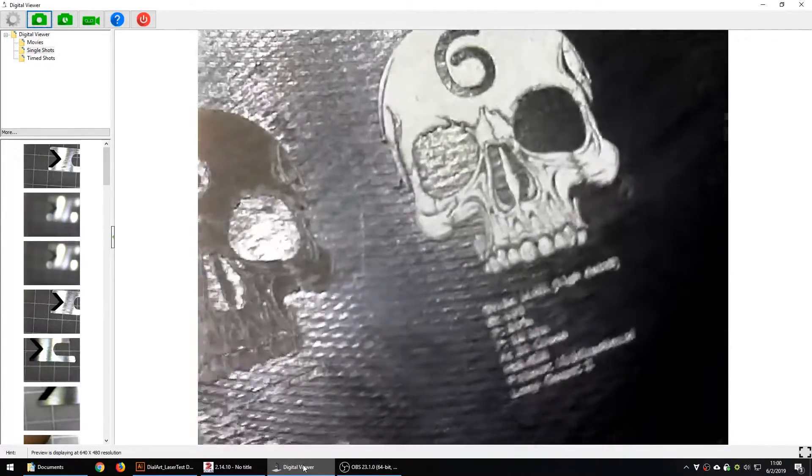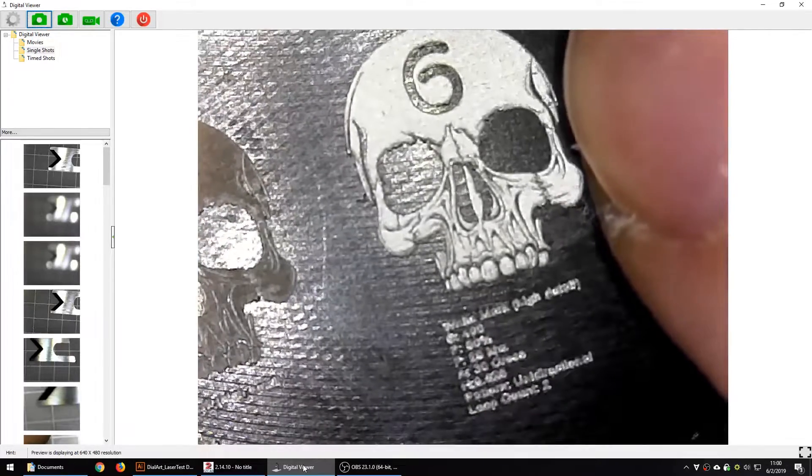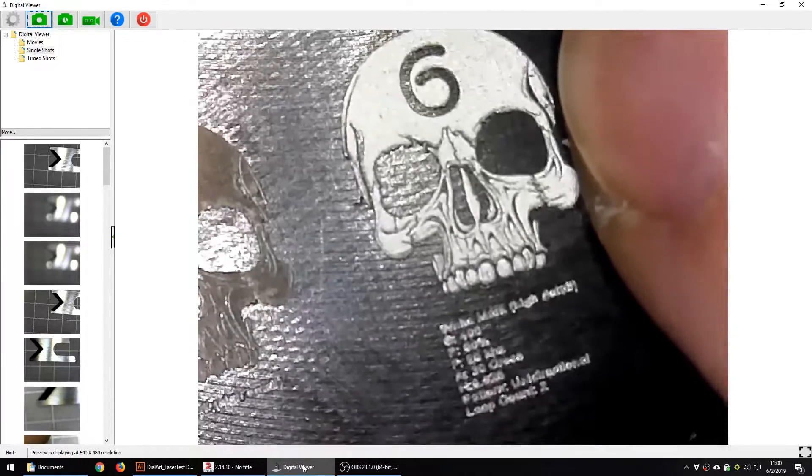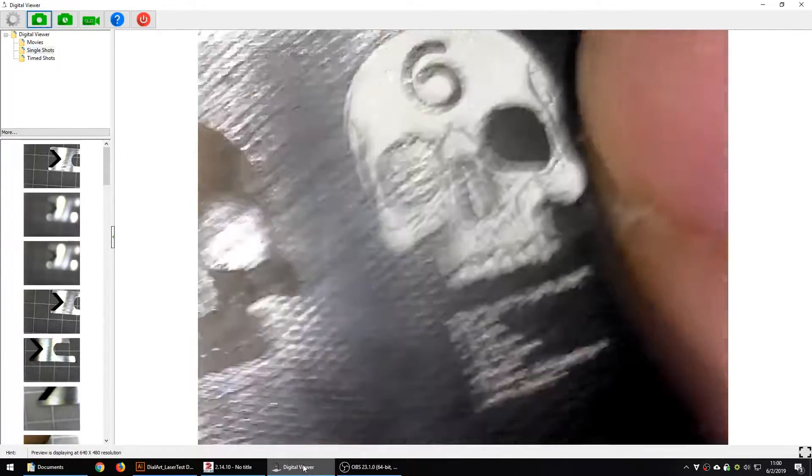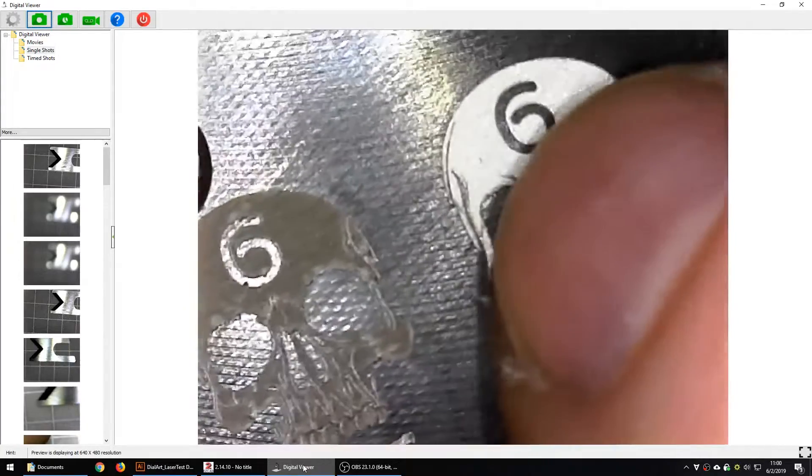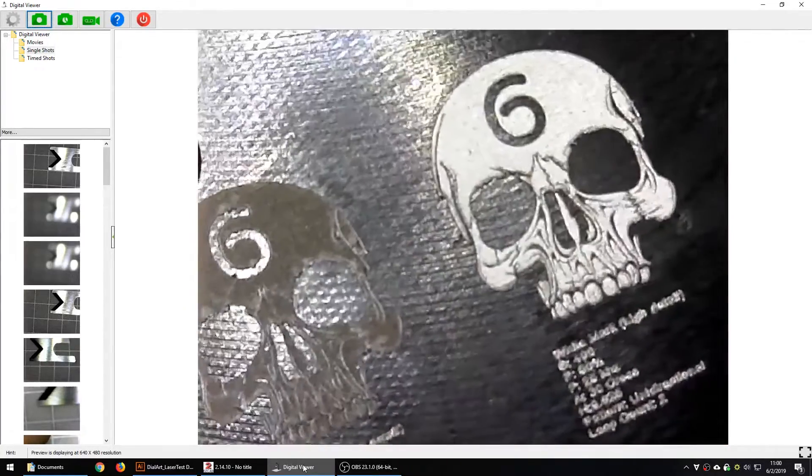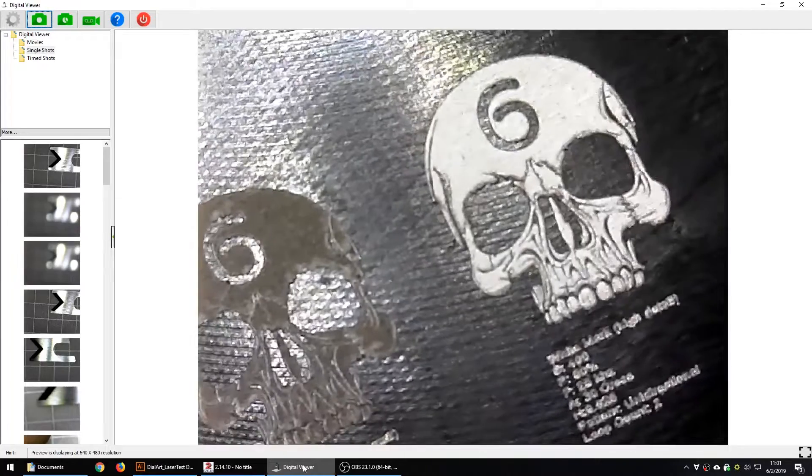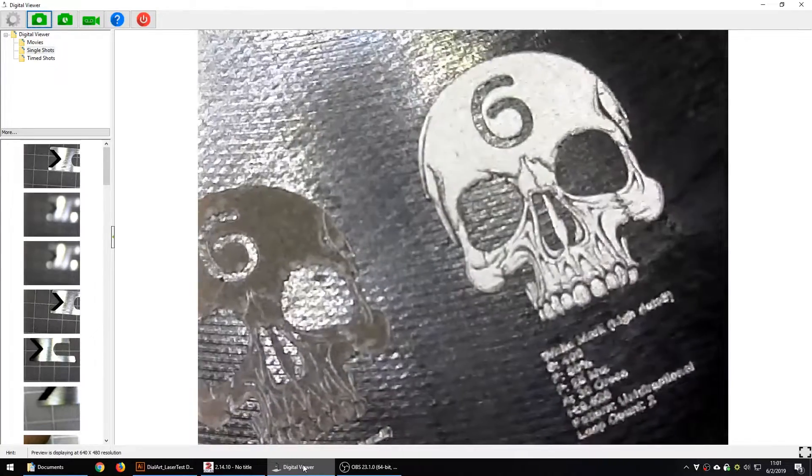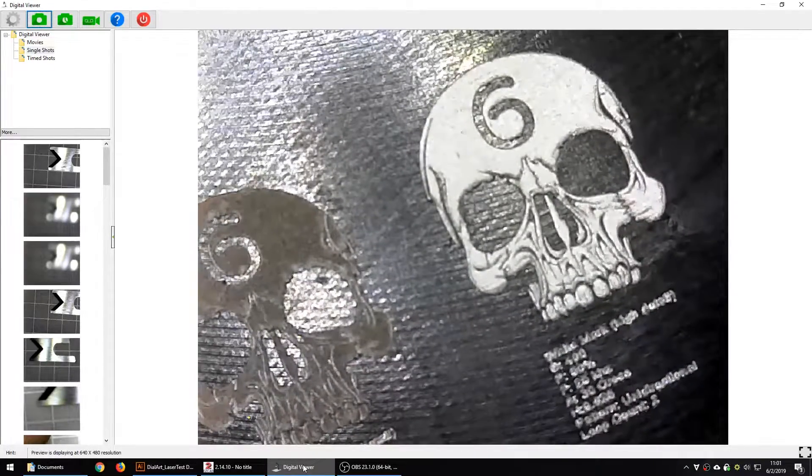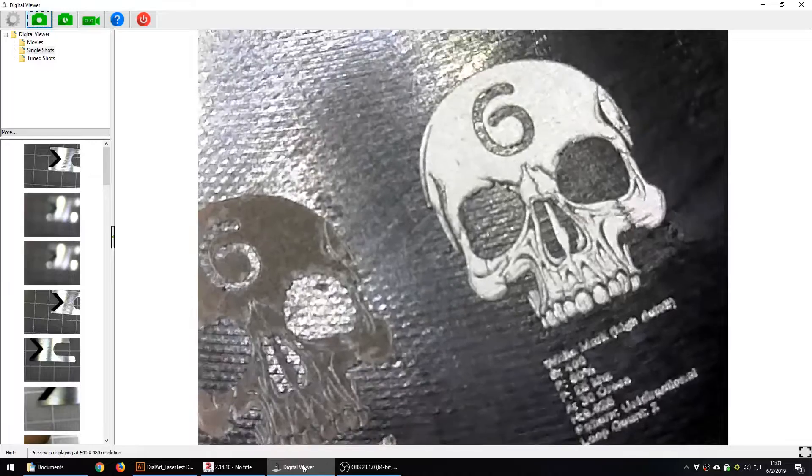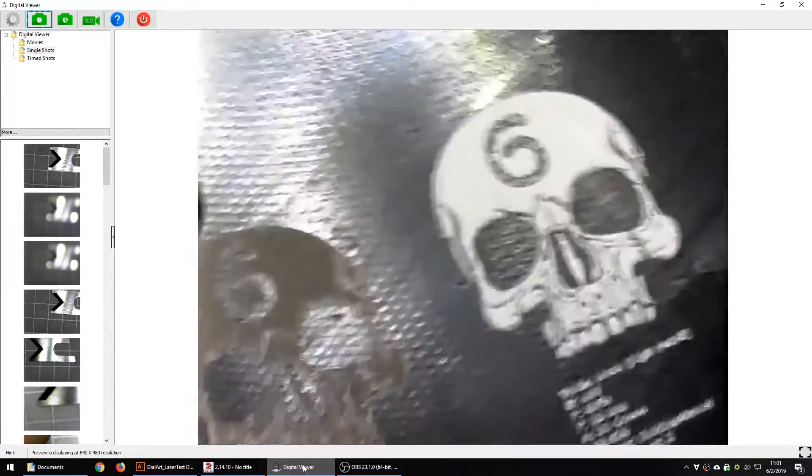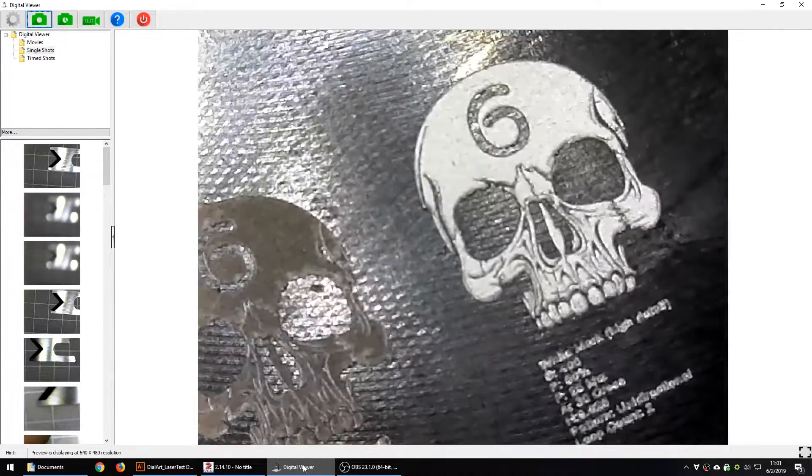One area I struggled, right over here, you can see these two little lobes coming down from the skull. Those would sometimes not fill in if I had the power settings wrong or if I had the hatch settings wrong. So I settled on a hatch of .025 millimeters, I tried less, I tried more, I tried significantly more and this is kind of what works the best.